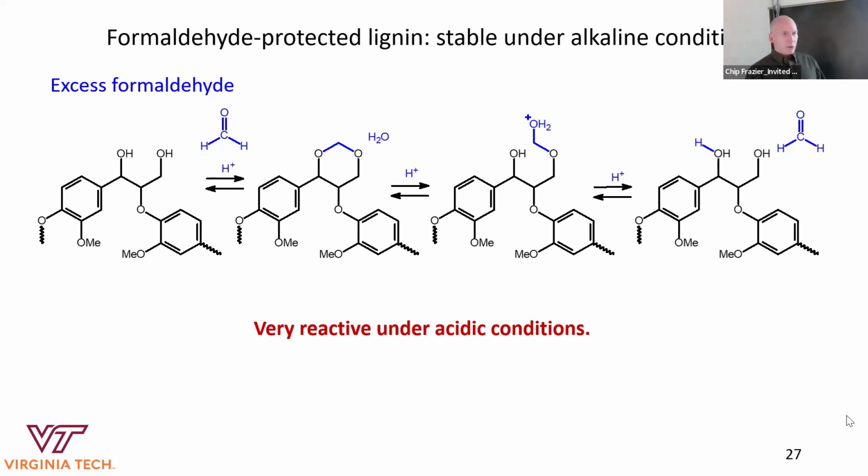Yeah, thank you for that question. So the yield of the lignin is very near the theoretical yield of, let's say, vanillin or beta O4 linkage. So if we assume 25% lignin content in an angiosperm, the lignin yield is over 90% on a theoretical basis. So it's very high. With gymnosperms or with softwoods, that yield plummets down to around 50% of the theoretical. So it's a huge reduction. And I forgot other aspects of your question. The curing, yes, that's very important.